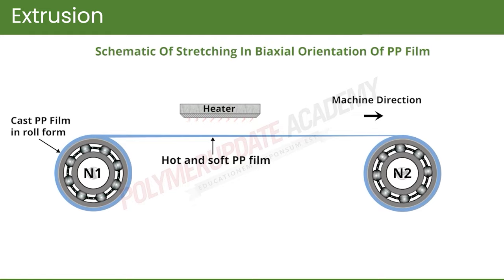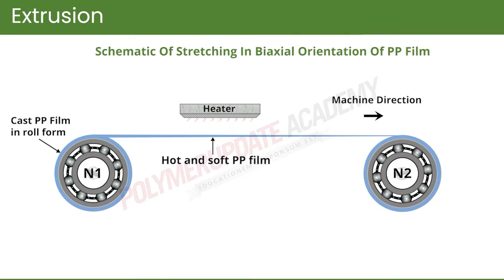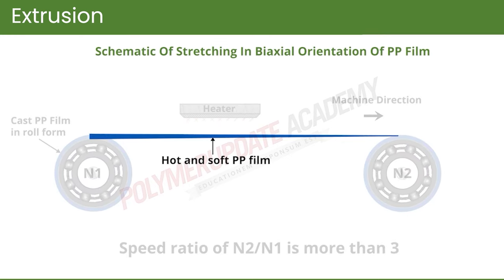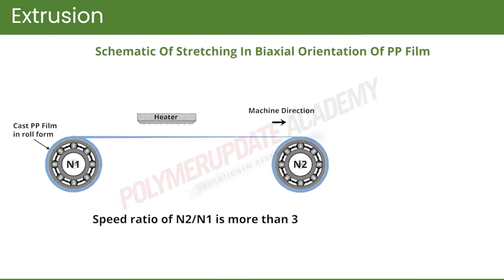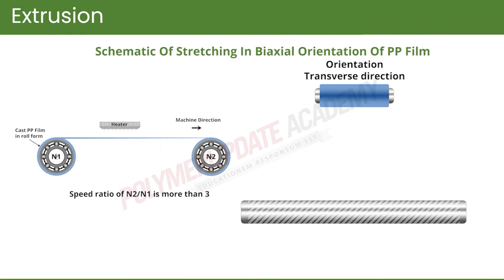The two rollers have different speeds; the second roller runs at a higher speed. So the film is unwound at one speed and wound on another roller at a much higher speed. Normally the ratio can be one to three. This way the film gets stretched — its length increases and thickness decreases. This is called orientation in the machine direction. After this, the film is cooled and then oriented in the transverse direction.